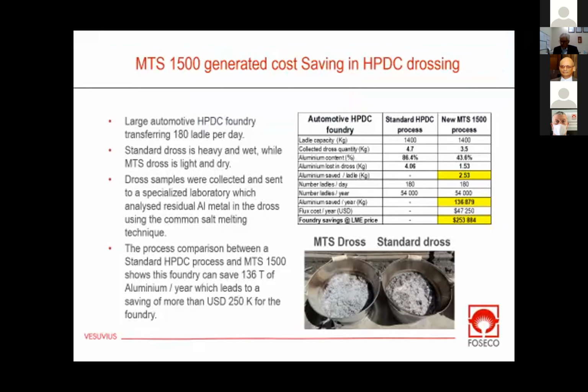When we averaged, we discovered that on average, when they transfer the melt, they have 4.7 kilo of dross generating on top of every ladle when they transfer from their melter to their casting furnace. We sent a sample of that dross to an outside lab, and the result came back that this dross contained 86% of trapped aluminum. So this is not oxide, this is aluminum droplets that have been turbulent, that have been trapped in the dross and are still aluminum in the dross.